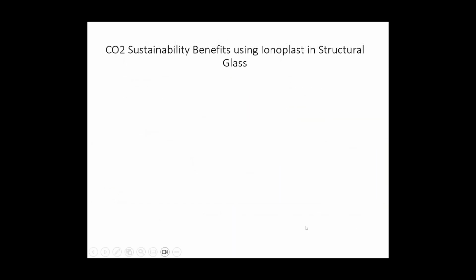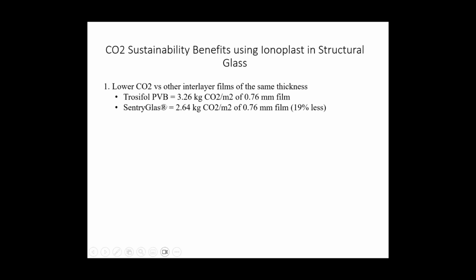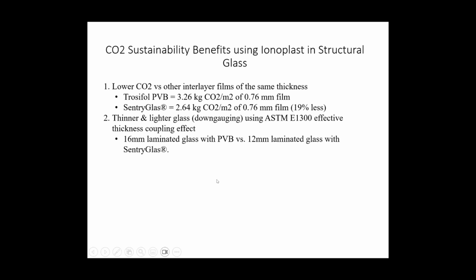I want to talk about structural glass. So with structural glass, just using the ionoplast for the same interlayer thickness, you reduce your carbon by 19%. But because of ASTM E1300, structural engineers can design the glass to actually downglaze it. So let's say you have a glass railing that requires 8mm glass with PVB. You might be able to get by with 6mm glass with the ionoplast. So actually you can reduce the carbon footprint of the glass itself.